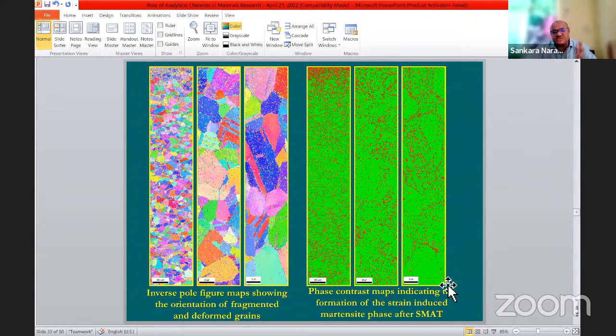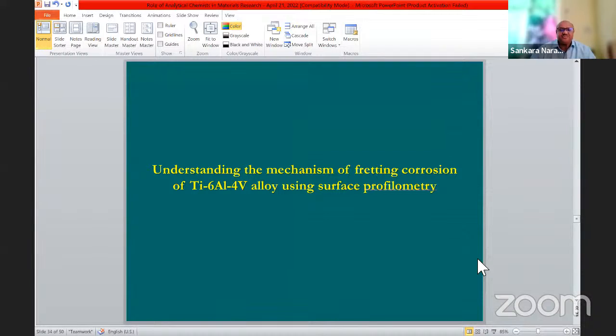So you can use electron backscatter diffraction pattern very effectively to understand the mechanism of deformation and the extent of phase transformation also. So it's a very good analytical method for materials research. We have also done the fretting corrosion of titanium alloy. Titanium alloys are normally used to develop implant materials, because as I said, titanium is highly corrosion resistant.